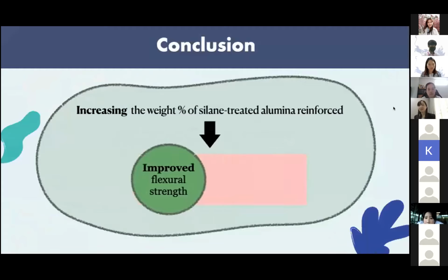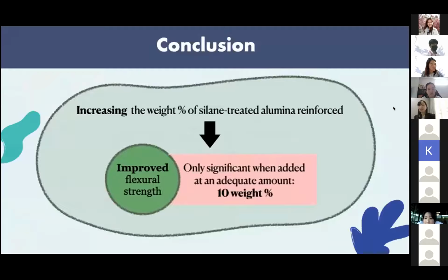Conclusion. Increasing the percent by weight of silane-treated alumina reinforcement leads to an improved flexural strength of heat-polymerized acrylic resin, but changes are only significant when added at an adequate amount, which is 10% by weight.